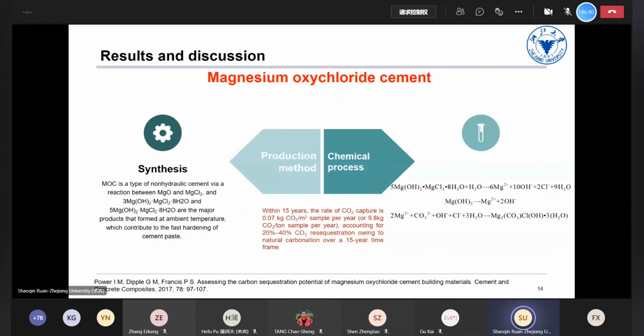That is magnesium oxychloride cement, and we call this MOC. MOC is a type of non-hydraulic cement formed by the reaction between MgO and magnesium chloride. Several very important phases, like phase 3 and phase 5, are the major products that form at ambient temperature, which contribute to the fast hardening of cement paste.